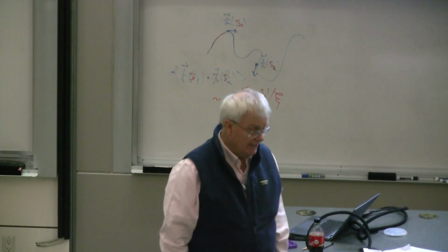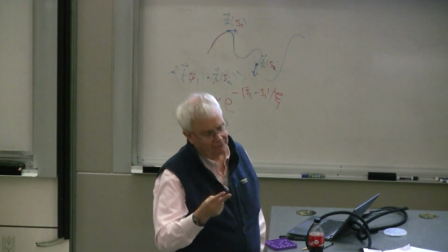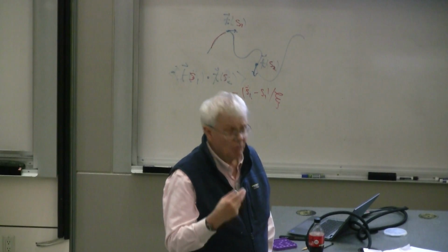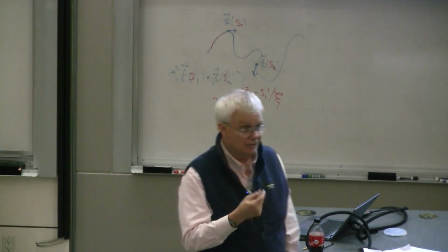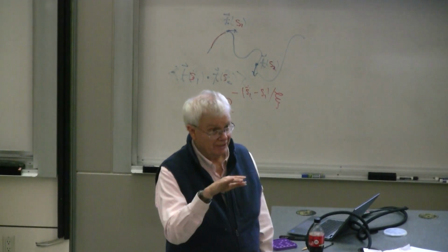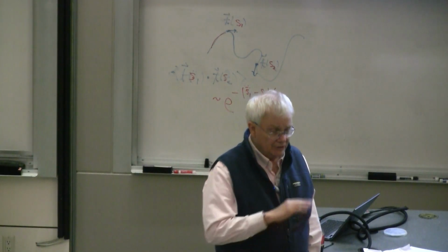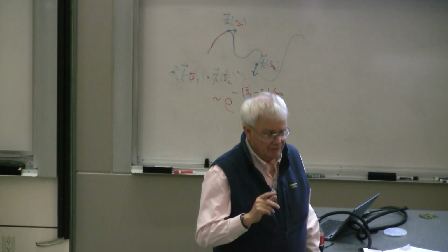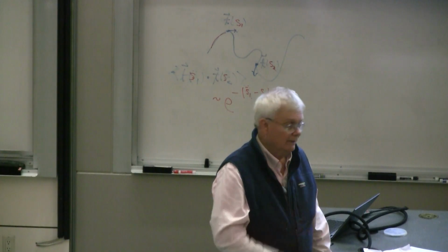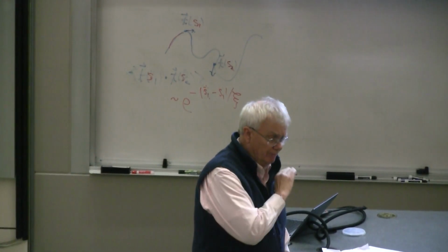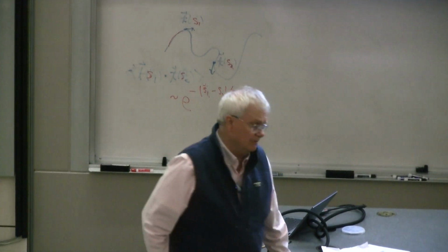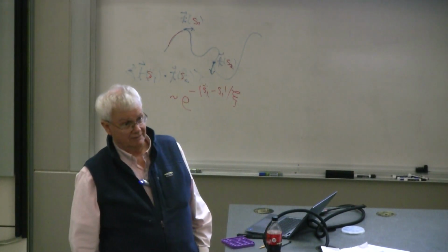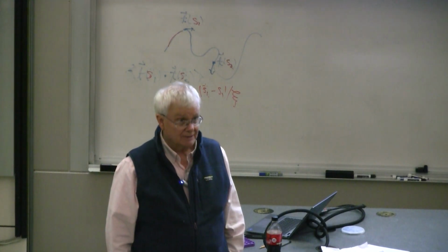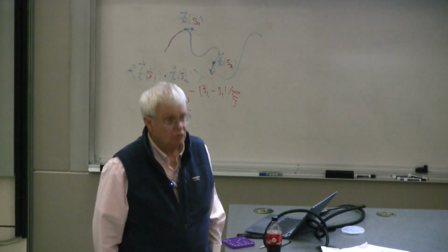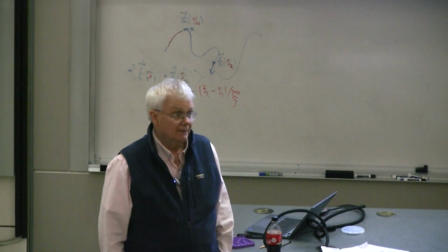If I want to get rid of this, I need to pump up that thermal length scale that I talked about that turns out to be 2 to 3 angstroms for freestanding graphene. For a general material, it depends very strongly on the bending rigidity. And the bigger the bending rigidity, the bigger that length is. And the bending rigidity goes like the cube of the thickness. And so I would just make thicker objects. And so, there's a trade-off depending on what you want.